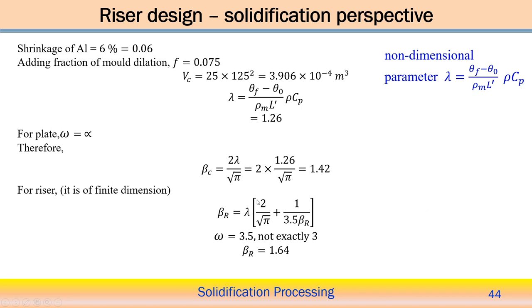Now, we can take the other parameters. Assuming the shrinkage of the aluminum, because aluminum is having 6% shrinkage during the solidification, which is changing phase from liquid phase to solid phase. But adding a fraction of the mold dilation will be there. So, some sort of adjustments with small dilation during the solidification process, we can take a little more than the actual values of the aluminum shrinkage. So, we can assume that F equal to 0.075, a little more than that of the 0.06.